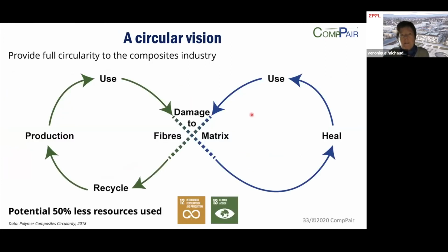And ideally, what we plan to do is really to have a circular vision, providing full circularity to the composites industry. So if you take a composite and you have damage only to the matrix through microcracks, you can actually heal, and then you can continue to use and rotate the material by regular maintenance, and the maintenance being only to heat up at 150 degrees for a few minutes, which could be even done locally by a drone, for example, if you consider a windmill.